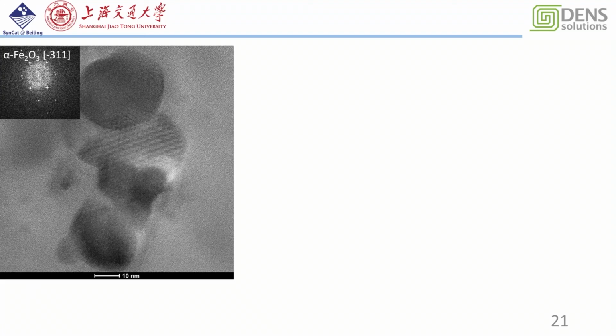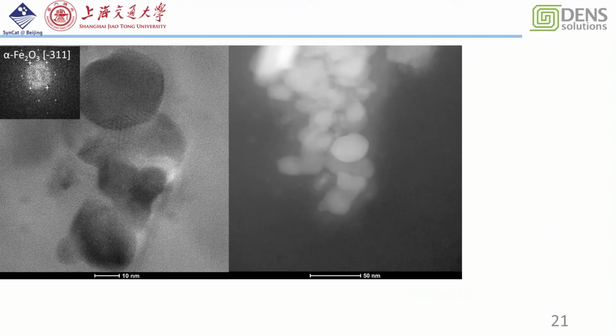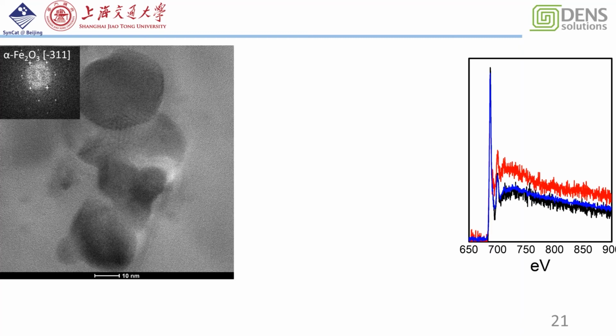And this is TEM images and STEM images. We can see the diffusion phases during the reduction process. And this newly formed phase is still the hematite. But when we use EELS, we confirm that this hematite is partially reduced. This has happened because this hematite partially removes the oxygen, and then the deformations happened following the reduction process. But at this stage, the complete reduction from hematite to the magnetite didn't happen.